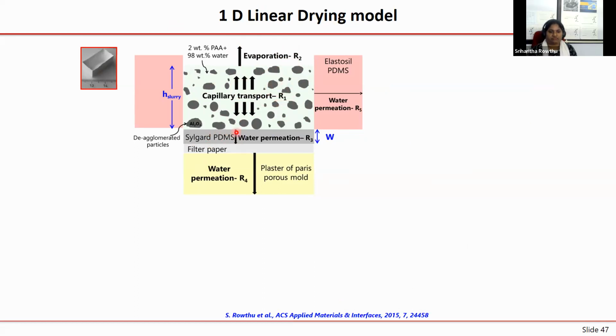And then the liquid is not entering, but vapor is entering. So water vapor permeation is given by R3. And then the filter paper and your plaster of Paris are very porous and very quickly absorb water. So R4 is not the rate determining step. So essentially, we need to look at R1, R2, and R3. Now look at a couple of things. One is the height of the slurry, that is how much you're pouring, and then W here is the thickness of my PDMS. Remember, in the literature, everybody was using W equal to 1.5 to 3 mm, etc. But in my case, I said let's go ahead and use smaller film thicknesses, smaller PDMS thicknesses.